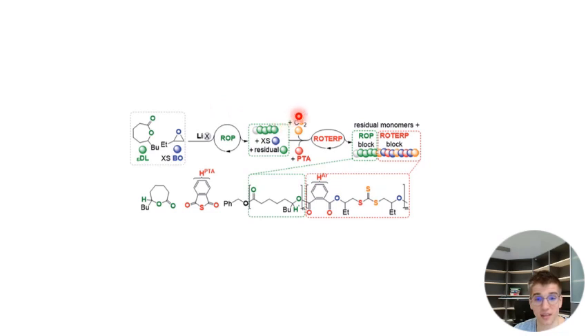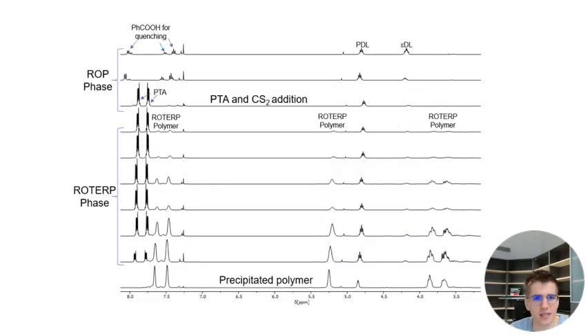This was the concept that was in the literature, and I now use this for this new terpolymerization. Here's some aliquot monitoring of the reaction mixture. Where does it start? Here it started. Here in the beginning, you see the monomer, the lactone, and the polydecalactone. Then, as the polymerization progresses, this gets a bit less intense, and this gets a bit more intense. I had to add some acid just to quench it to get an NMR. Otherwise, you take an aliquot and the polymerization continues in the NMR tube, so you usually have to add something to make it stop.